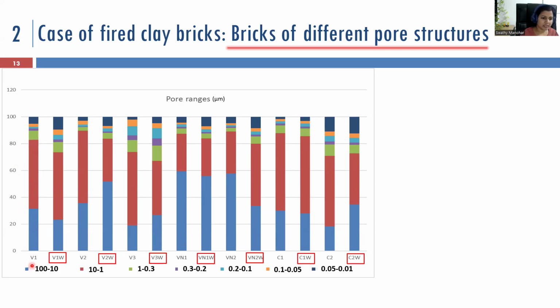For the V1 sample, the blue color, which is 30%, is the macroporosity, pores between 100 and 10 micrometers, and the top is the microporosity. Everything in these red boxes are the same samples as before, which are after weathering. So this is V1 before weathering and this is after weathering.